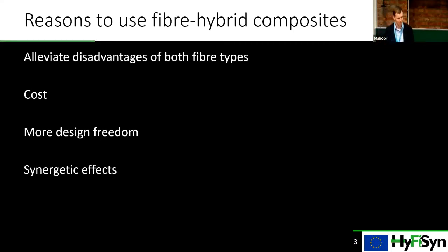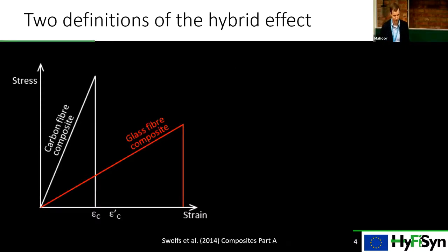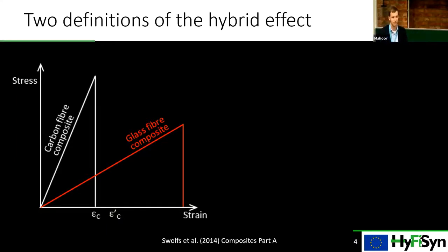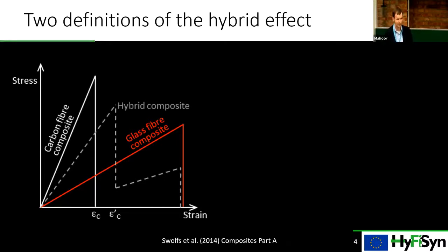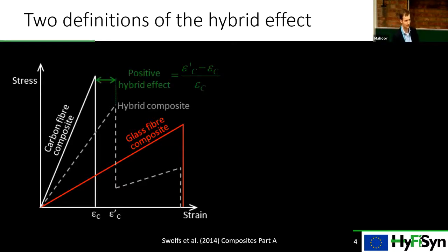I will typically call these hybrid effects — essentially just another word for a synergetic effect. There are in principle two different definitions for the hybrid effect. The first is often referred to as the classical hybrid effect, discovered somewhere in the early 70s. Here you have a carbon and a glass fiber composite, and if you put them together you get the hybrid composite with behavior somewhat in between. The striking difference is that the failure strain of the carbon fiber plies in that material is now higher — that increase in initial failure strain is the classical hybrid effect, expressed as a ratio of the new failure strain versus the old.